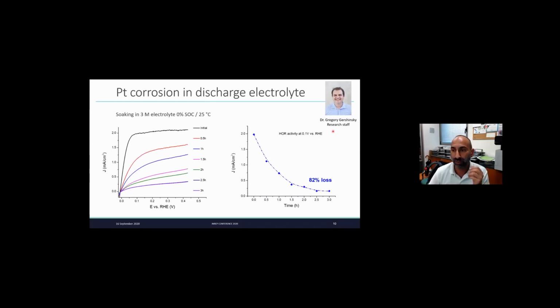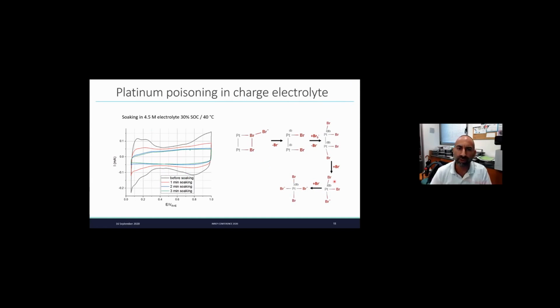So a few years ago with Dr. Gregory Gershinsky, we did the experiment. So what we did was soaking the platinum inside an electrolyte at 25 degrees, 0% state of charge, kind of low concentration, 3 molar. And what we've seen is a decrease of the platinum activity with time. So here you have the initial activity and then it goes down. And here we've plotted like that. And after a few hours, you don't have any more platinum on top of the layer. So the mechanism is like that.